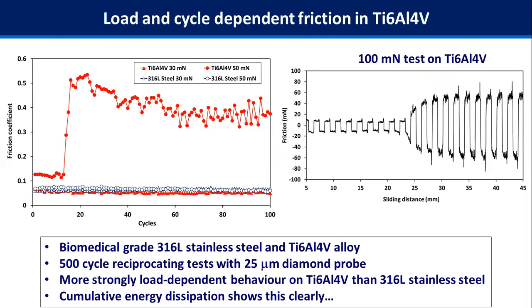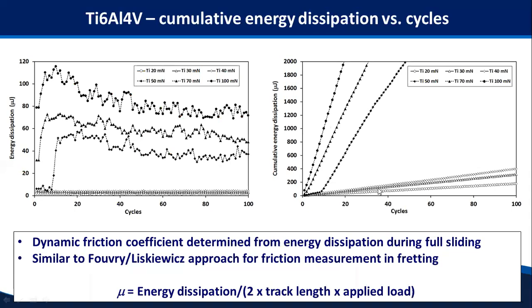So if we move on now to the biomaterials, stainless steel has a very ductile response when you look at these SEM images of its wear tracks, and very low friction. But in contrast, the titanium alloy, similarly ductile at low load, has an abrupt transition at high load. So you can see here on the left in this example at 50 millinewtons, it's relatively low friction, and then suddenly after about 15 or so cycles, you get an abrupt change to a high friction regime really within a small number of cycles. You can also see this clearly in a high load test on the right. So cumulative energy dissipation can also be used to follow this, and you can see quite clearly this transition as a function of load and cycles.